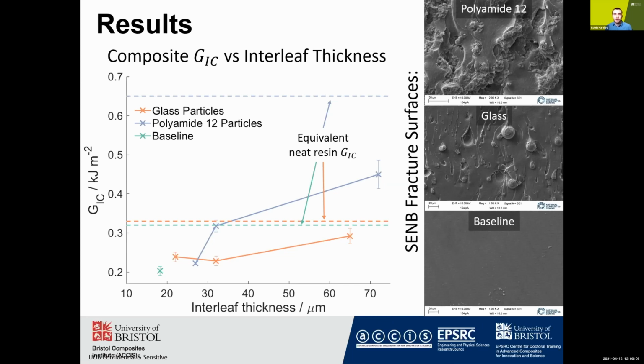So looking at the neat resin results, and these are the dotted lines, you can see that glass particles are not very effective tougheners, as they can only toughen through crack deflection mechanisms and by acting as stress concentrators that enhance toughening mechanisms such as shear banding that are already present in the particle-free resin. The polyamide particles, on the other hand, have a significant toughening effect, which can be attributed to a combination of their ductility and interfacial strength with the epoxy, which basically allows them to tear and plastically deform as the crack propagates past them.